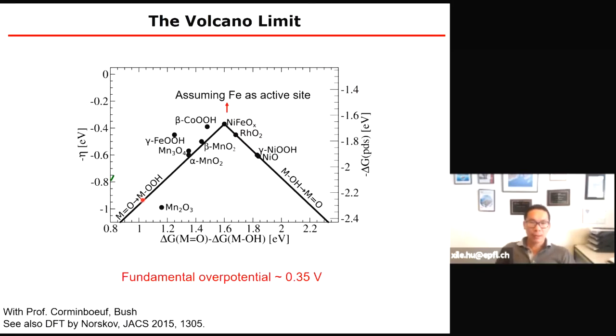The same kind of volcano plot can be made for various metal oxides, mainly based on earth-abundant elements, things we like to use: manganese oxide, iron oxide, nickel oxide. Indeed, for some of them the formation of the metal oxy radical is too easy, so the hydroxy attack is too difficult and becomes rate-determining. For some of them, the formation of the metal oxy species is too difficult, so that gives a lot of overpotential. On the top of this volcano plot is nickel iron oxide, if you assume iron as the active site. Calculation suggests this will have 1.6 eV, and so a minimal overpotential of about 0.35 eV. This suggests that this catalyst would be the best catalyst one can have for OER.